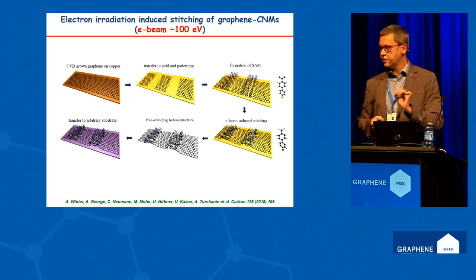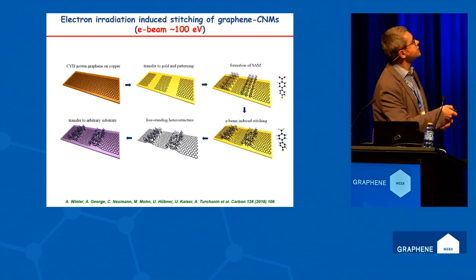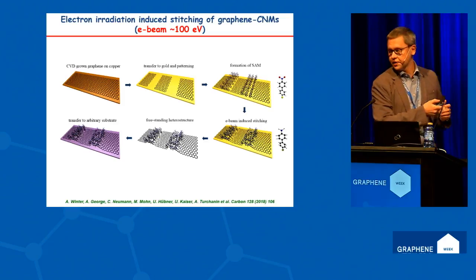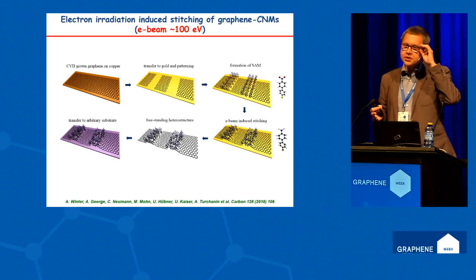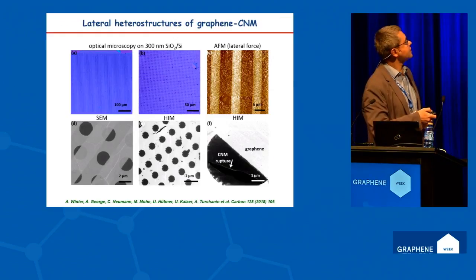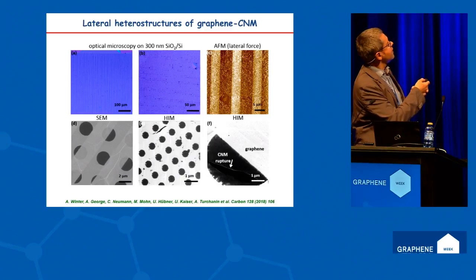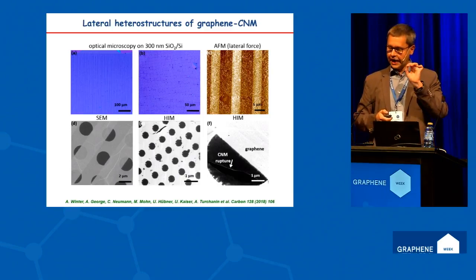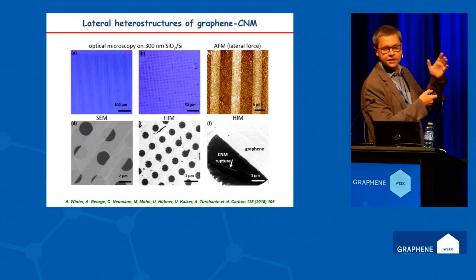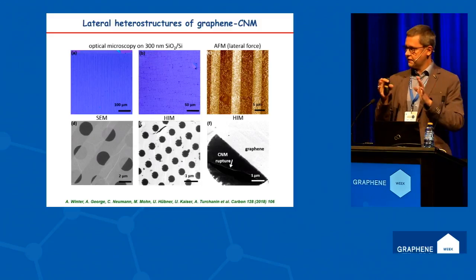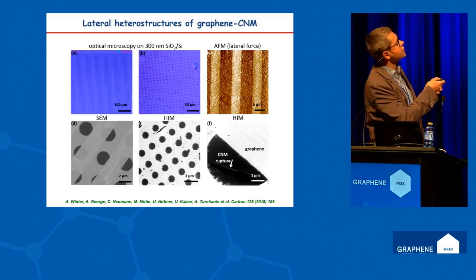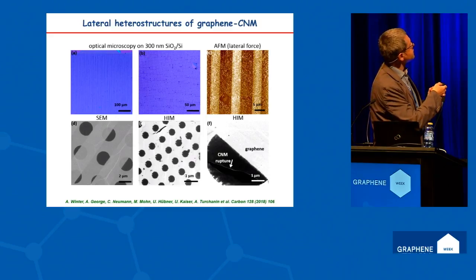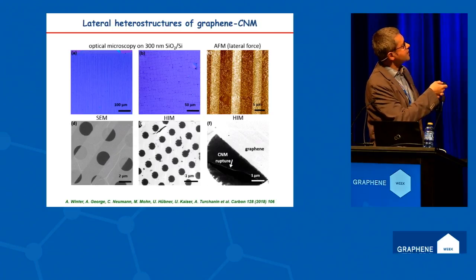You not only cross-link the molecules with each other, converting them into carbon nanomembranes, you also introduce stitching between the edges of the graphene ribbons, or any graphene structure, put it this way, and carbon nanomembranes. This is an example of a matrix of dielectric carbon nanomembranes where graphene ribbons are incorporated inside. These are graphene dots inside the dielectric carbon nanomembranes. These materials have very different mechanical properties. That's why in lateral force measurements you can very well recognize hard graphene areas and soft carbon nanomembrane areas. This is an SEM image of graphene ribbons and carbon nanomembrane ribbons, and this is a matrix of graphene with dots consisting of carbon nanomembrane.